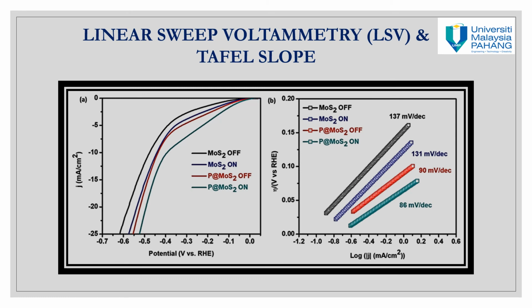So these are the results of LSV and Tafel slope. The LSV was performed in both dark and light on conditions. As you can see from figure A, the green line shows the lowest overpotential. Generally, low overpotential means superior catalytic activity. So the phosphorus doped MoS2 during the light on condition shows great activity.